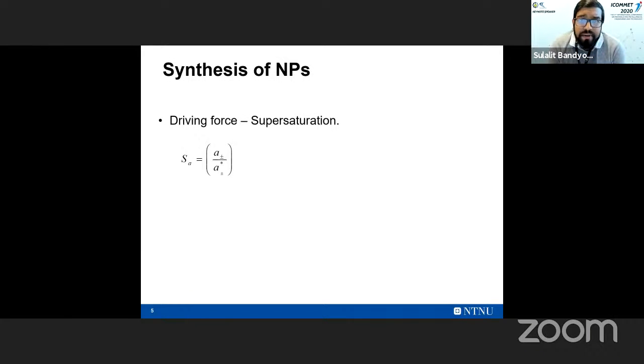In order to synthesize nanoparticles, the very driving force is the supersaturation. Supersaturation is defined in terms of the activity of a certain molecular species in the solution divided by the activity of the same species in equilibrium conditions. So in order to form nanoparticles, there should be a driving force in terms of supersaturation. Once you have established that driving force, the first events would happen. The first nuclei would form in a step called nucleation.